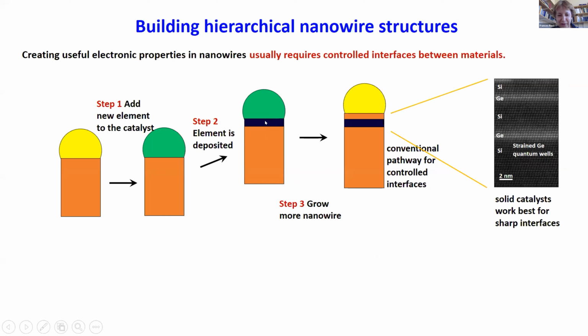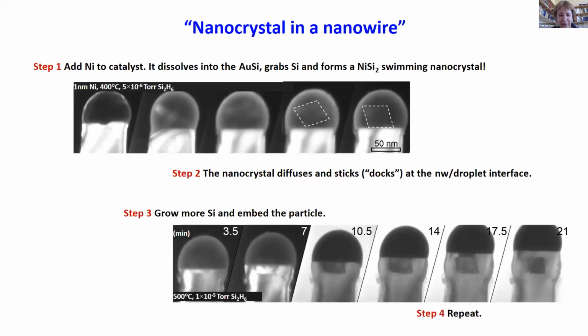Let's grow some nickel. We'll form nickel silicide. That will be a really good electrical contact for our nanowire. So we put the nickel in, and instead of growing a nice layer horizontally at the interface, we got this floating island. It doesn't really show up here, so I drew a boundary around it. But basically, this object forms, floats around for a bit, and eventually sticks onto the interface.